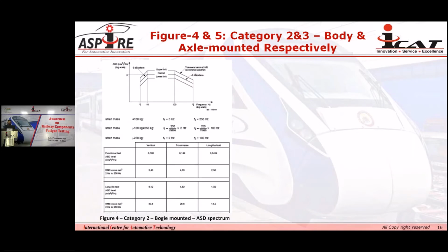So first let's discuss category 2 bogie mounted equipment. If the mass of the test component is less than 100 kg, in that case the frequency is fixed, that is 5 to 250 Hz. And again, if the mass of the test sample is between 100 kg and 250 kg, in that case, again, we have to calculate the lower frequency and higher frequency. In this case, the formula is different compared to the previous case.